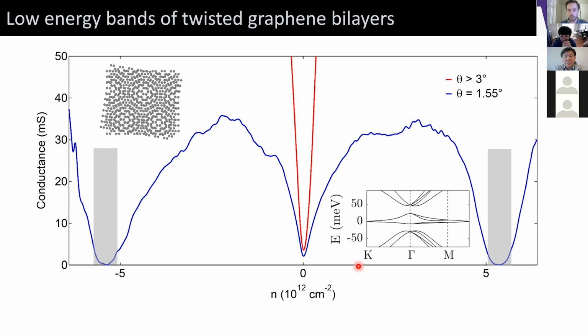So the hybridization of these two metallic graphene bands leads to these low energy Moiré subbands, and then they're isolated from the higher energy dispersive bands by some energy gap. And so this energy gap is responsible for the insulating behavior. And again, this is single particle level. And by convention, I'll call these plus or minus n sub s, or n sub superlattice, basically the number of electrons or holes necessary to fill these low energy flat bands.